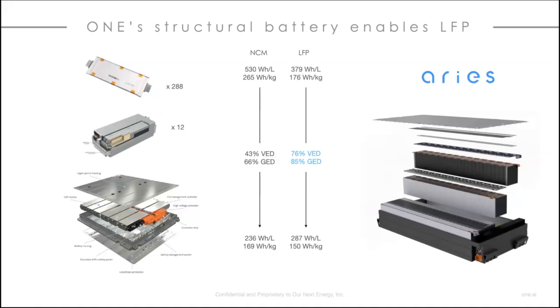That architecture results in a typical NCM cell at around 530 watt hours per liter, losing much of its energy density through cell to pack at only 43%, but also gravimetrically at 66%. So the net result is a 236 watt hour per liter system level performance of energy density and 169 in gravimetric terms. What we've done with leveraging LFP and a high cell to pack is retain a much higher fraction of the initial cell chemistry's capability at 379 watt hours per liter, which is a very good chemistry achievement for LFP.